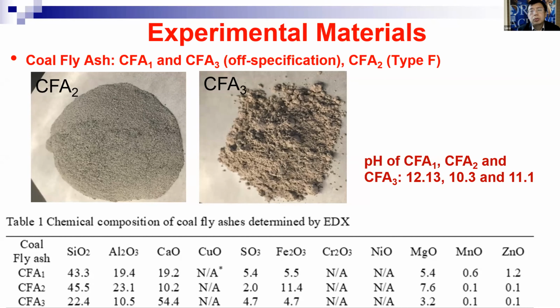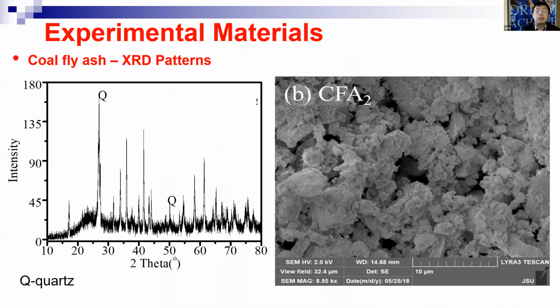We also measured the pH of this fly ash, about 10 to 12. So this is the fly ash. Now we have steel slag and fly ash. We can also use XRD and SEM to characterize the materials. If you look at the SEM of the fly ash, you can see there is a lot of void space. Basically, we need that kind of void space.